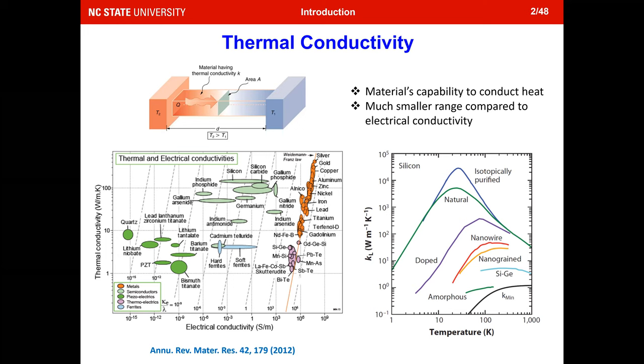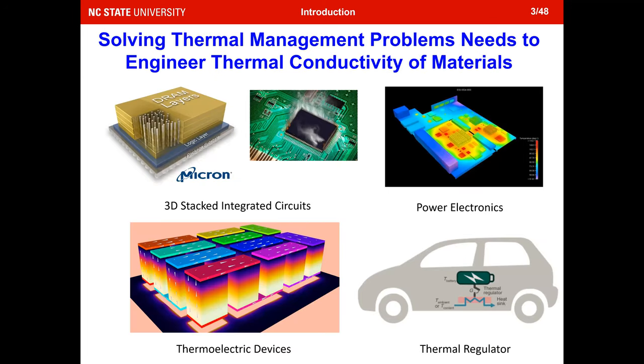Despite that, in silicon, people have been working to tune the thermal conductivity using different techniques, right? From the natural crystals, silicon has a thermal conductivity of 140. You can use doping, you can use nanoscaling techniques, you can use alloys, you can make it amorphous to tune the thermal conductivity. A lot of engineering problems have similar needs, especially when related to thermal management. You need to control the temperature in all these devices.